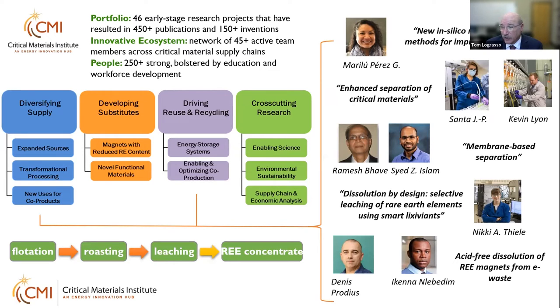We then take those into the lab, synthesize them, and validate those predictions. We apply them to different separation techniques. In this particular case, membrane-based separations have proven to be quite effective for rare earths, both in the upstream activities as well as recycling. One of the holy grails is, rather than leaching everything all at once, can we go in and selectively dissolve the rare earths that we want?